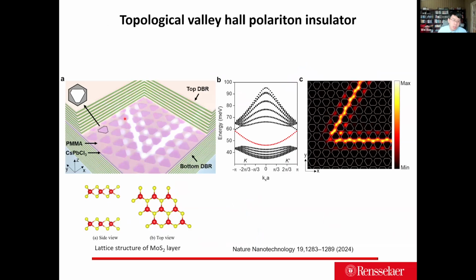Inspired by this, we want to first demonstrate a pure topological edge state. Here we design our polariton cavity. Essentially we have the DBR, and then we choose cesium lead chloride, which is the first material that demonstrated room temperature polariton condensation in the halide perovskite community. We optimized the growth method and tried to make the sample really large, in both solution and CVD samples. We also break the C6 symmetry from a graphene-like photonic lattice into a MoS2-like one, with a big atom and a small atom. At the same time, we use the type B, with the big atoms adjacent to each other, so this has a tighter confinement on the edge state. Then this type B topological edge state starts to form, and this is the simulation one can see.